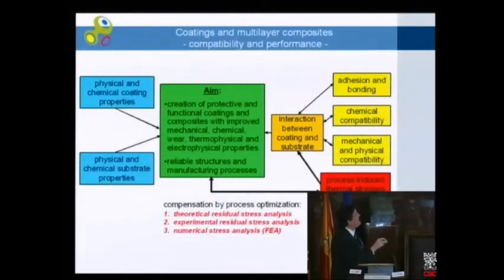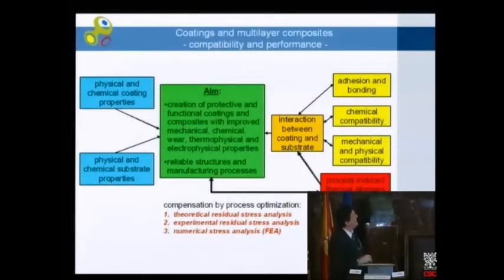And one basic reason is that there is a distinct interaction between the two materials, between the coating and the substrate. And not only under operational conditions, not only under testing conditions at room temperature in a lab, no. Also in the conditions of manufacturing, that means in the processing conditions. So therefore we need a deep understanding of adhesion, of chemical compatibility, and the complete set of physical compatibilities. And if you see that people combine lightweight alloys with ceramics, and you see this large difference in thermophysical properties, for sure we have to handle a problem of high thermal stresses and residual stresses as they result from the process and its histories.